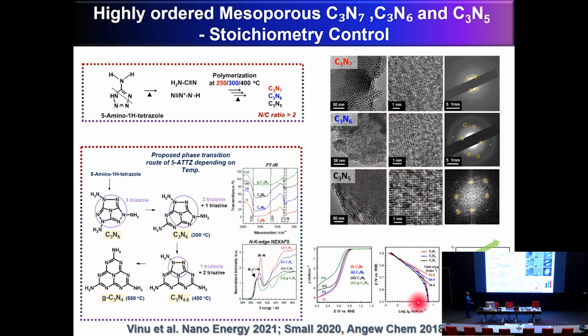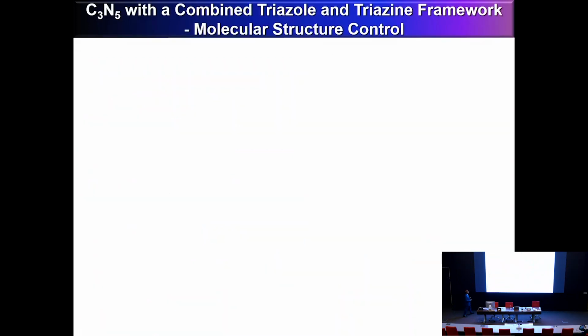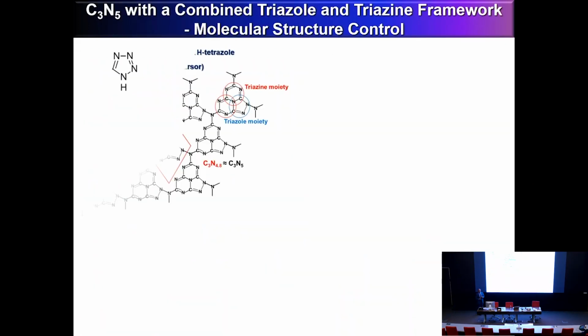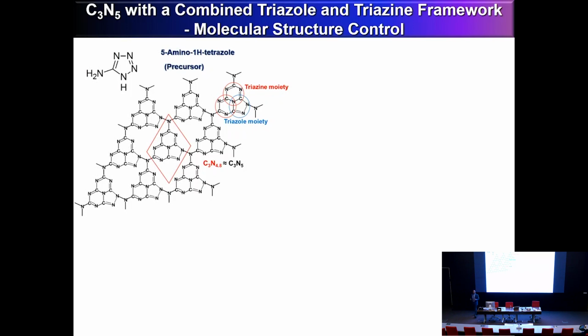When you have a material with a high nitrogen content, the current density that you are getting is much, much higher than the carbon nitride material with less nitrogen content, right? So what about the stability of the material? Whenever you talk about carbon nitride with high nitrogen content, they may say, oh, it will explode. So ladies and gentlemen, I just wanted to tell you, we prepared this material at a temperature of 400 to 550 degrees centigrade, and it is highly stable at room temperature.